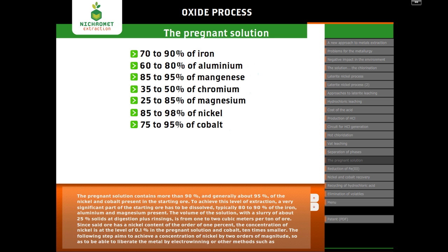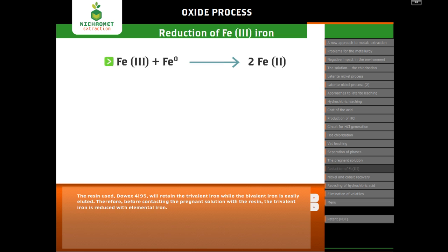Also, the other elements that are the main consumers of hydrochloric acid, such as iron and aluminium, can be involved in hydrochloric acid recovery by hydrolysis, while magnesium chloride will need sulfuric acid treatment. This concentration of nickel and cobalt from the pregnant solution can be achieved by ion exchange resins or solvent extraction. The resin used, Dowex 4195, will retain the trivalent iron while the bivalent iron is easily eluted. Therefore, before contacting the pregnant solution with the resin, the trivalent iron is reduced with elemental iron.